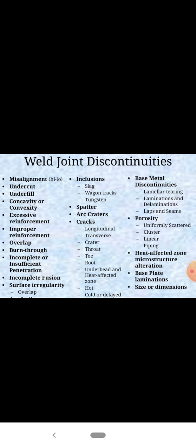And I'm just going to read out the list: the misalignment, high and low, the undercut, the underfill, concavity or convexity, excessive reinforcement, improper reinforcement, overlap, burn through, incomplete or insufficient penetration, then incomplete fusion, surface irregularity that is leading to the overlapping, and slag inclusion, kind of surface cracks, and distortion, and the longitudinal, transverse, crater, throat to the root, under bead, and heat affected zone, the hot and cold or the delay.